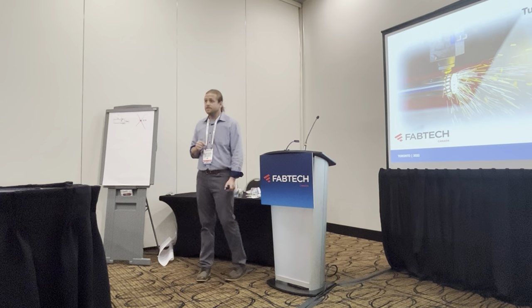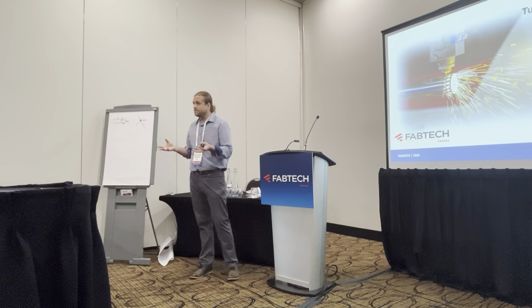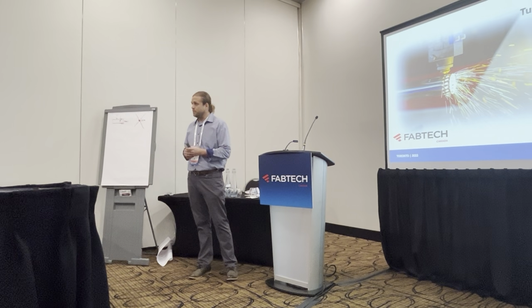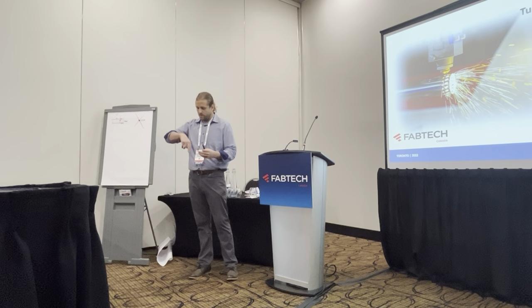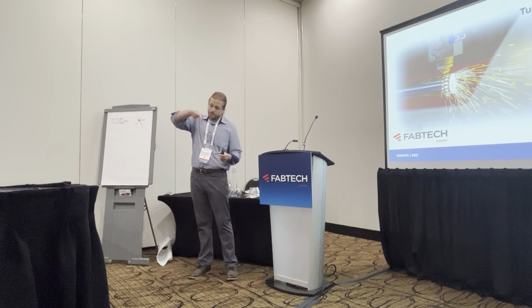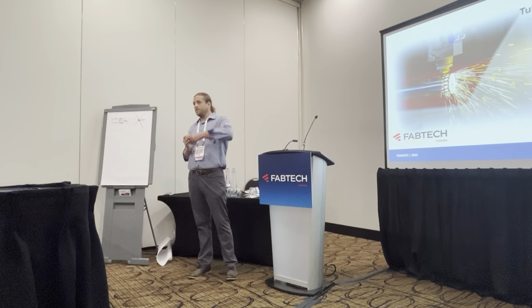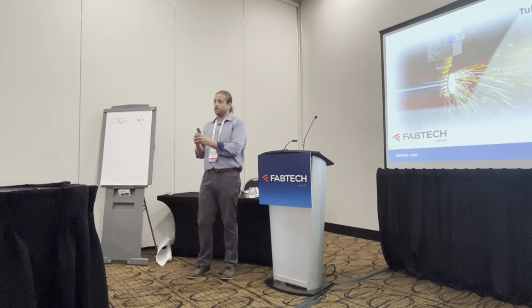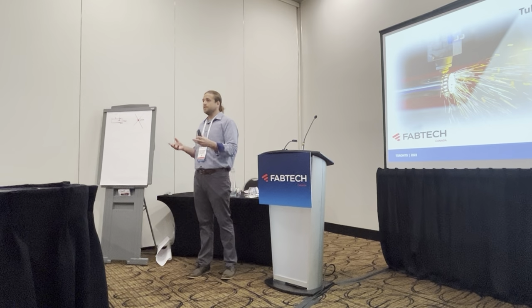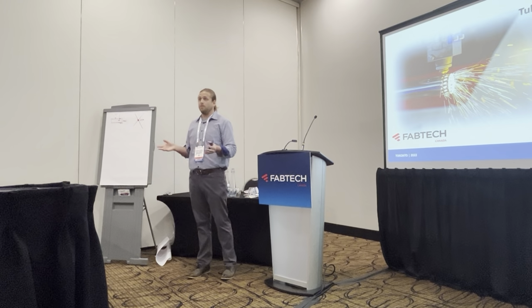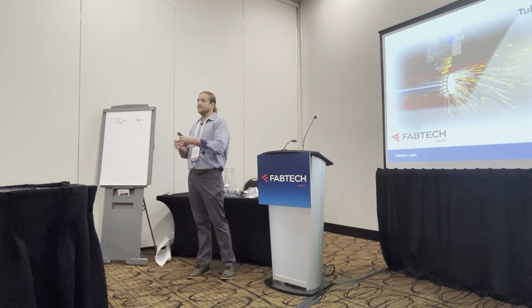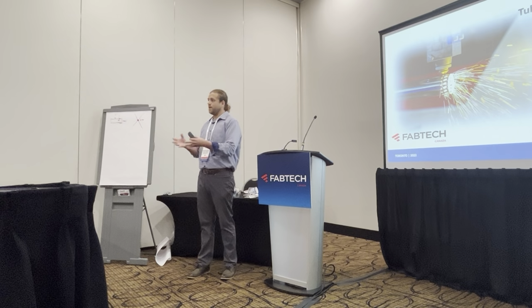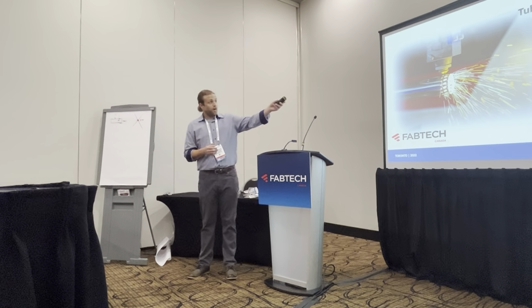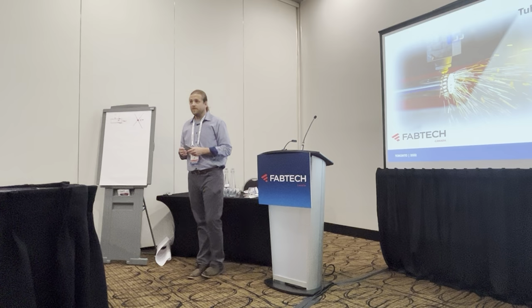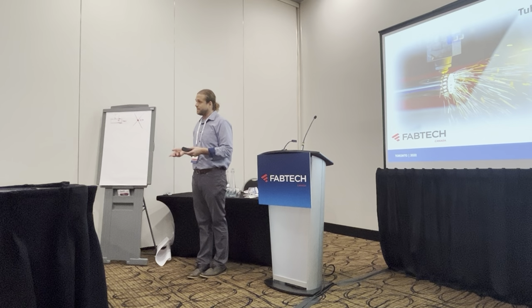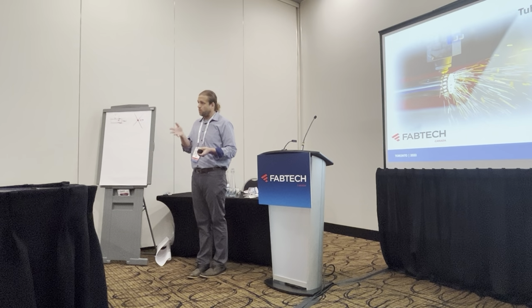Weld seam detection, that's another huge one. So in bending, weld seam plays a critical role. If you put the weld seam in the crush or the stretch zones of the tube, if you put it in the stretch zone, sometimes the weld seam can actually crack open, but it also can affect your developed length. In bending, you need a developed length, kind of like you need a developed flat sheet metal. Weld seam detection plays a critical role in that, because without a laser weld seam detecting, it would just place the weld seam all over the place.